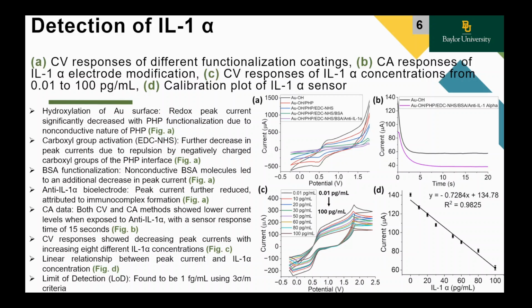15 seconds. In figure C, CV responses show decreasing peak current with increasing 8 different interleukin-1 alpha concentrations. A linear relationship between peak current and interleukin-1 alpha concentration was found from where the limit of detection, LOD, was calculated to be 1 femtogram per milliliter using 3 sigma per m criteria, where sigma represents the standard deviation and m is the slope of the calibration curve.